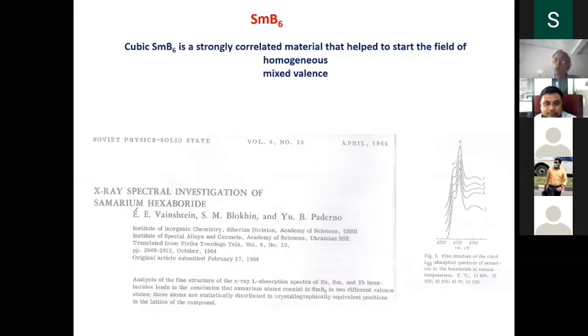So these they could not understand. Look, there is only one site for samarium. How is it possible that you get 2 lines here in the X-ray absorption spectroscopy? So they did not understand. They probably felt the sample was inhomogeneous. There's a possibility that some places are 3+, some places are 2+, so chemical inhomogeneity in the sample. They left it like that.